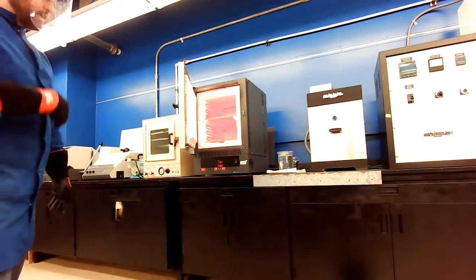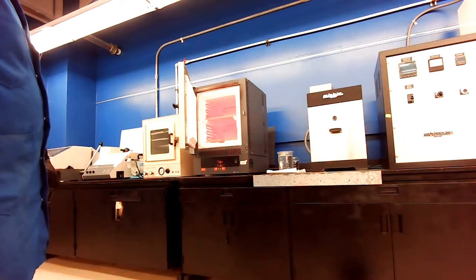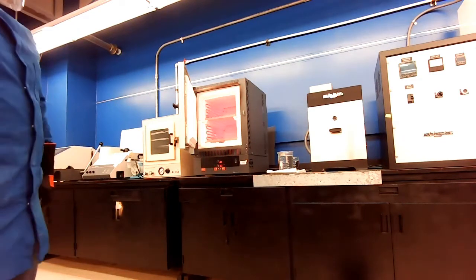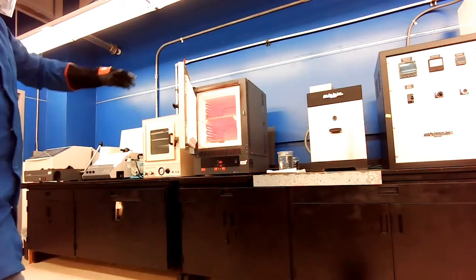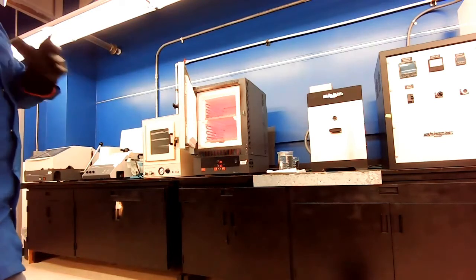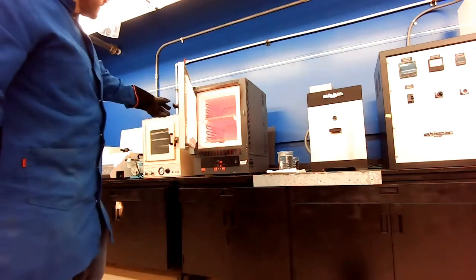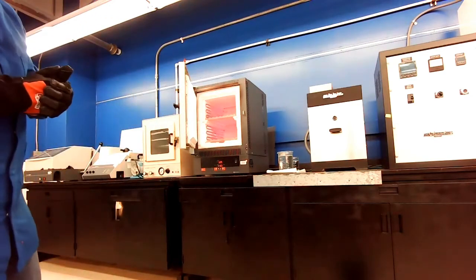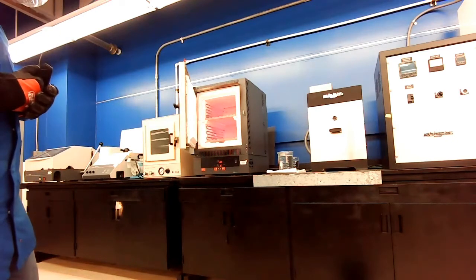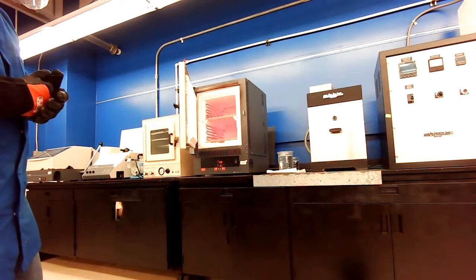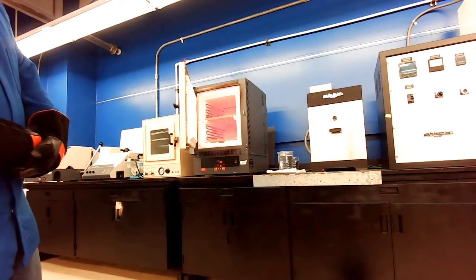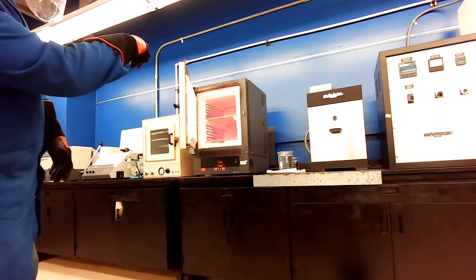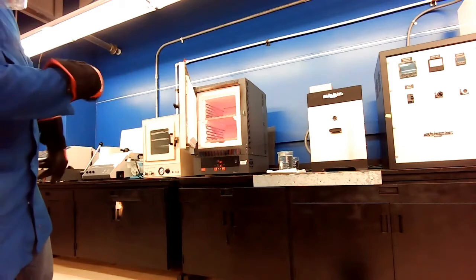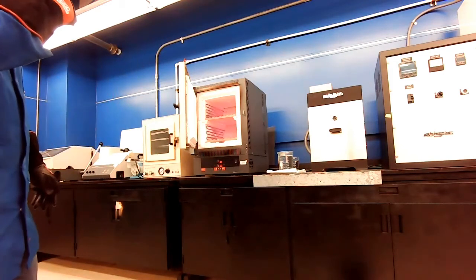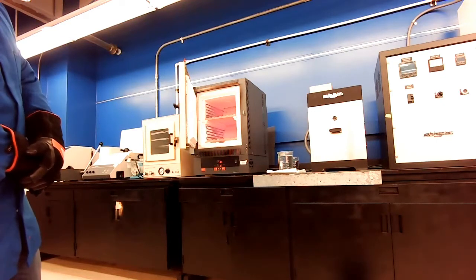So we're down at about 800. When this gets a little bit below 700, I'm going to close it back up. Okay? I don't want it to go too much lower. I don't want to have any weird transformations. I just want to be in that temperature range where that pearlite can form. So we're at about 750 in the furnace. It's a little bit hard to see on this camera, but in the back left, there's a thermocouple, which is reading out that temperature. Okay, so it's telling me what it is inside of that area.